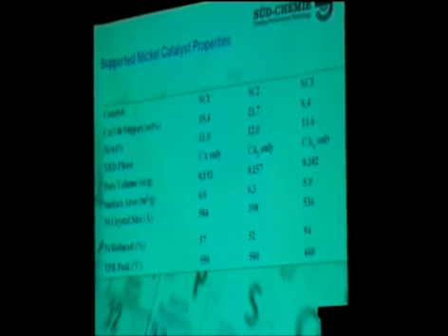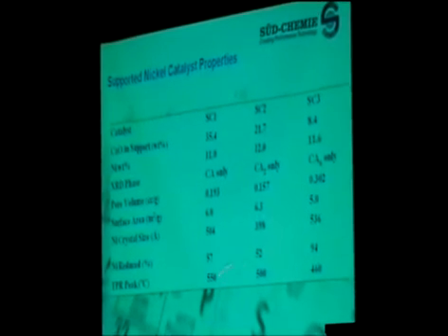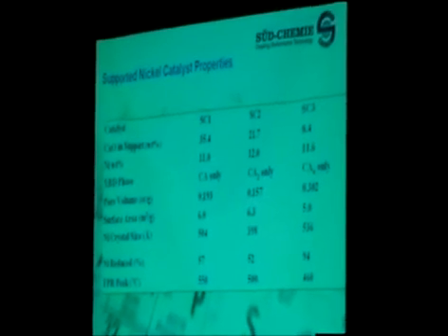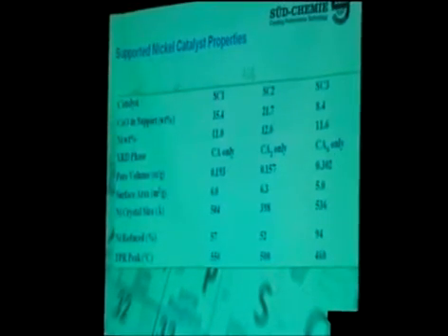And one thing I need to mention is the percentage of nickel that can be reduced. You can see here, this hex aluminate, pretty much 100% can be reduced, but on this higher calcium support, only about half of the nickel can be reduced. And from the TPR, you can see here as well, this one can be reduced at lower temperature. I have to keep their curves for later.